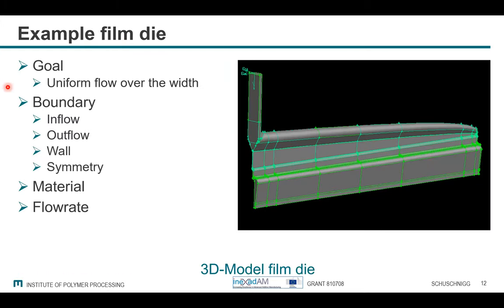For example, here I have a film die. I only use one half of the film die because the second half, which would be here, is the same. The goal is uniform flow over the width out here. With the boundaries, we have an inflow, outflow. Here we have wall adhering, and here we have the symmetry. We have to define the material and the flow rate, and then we can go to the simulation.